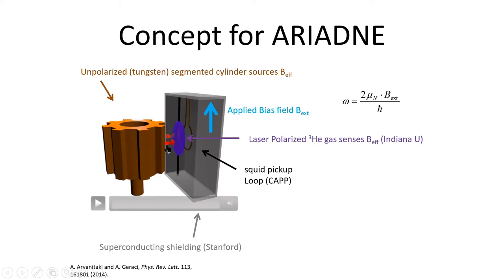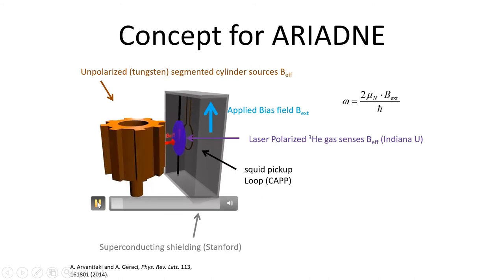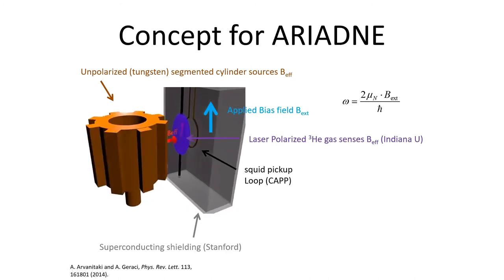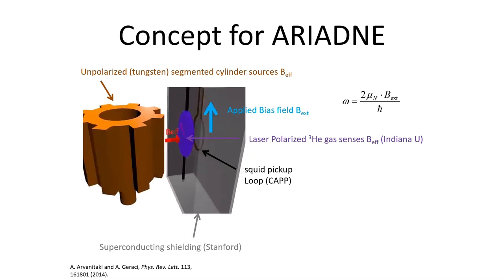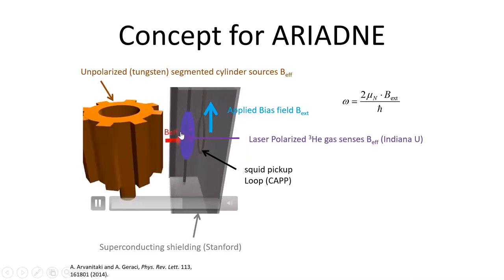And so the sample volume is enclosed in a container which is coated with superconducting shielding. And so that superconducting shielding will prevent regular magnetic fields from penetrating through, but not prevent this axion-induced magnetic field from penetrating through. So the idea is that we take this source mass and we arrange it so that it has a gear shape and has these teeth. And so as we spin the source mass cylinder, the teeth of the cylinder come by, and every time a tooth comes by, it basically modulates the strength of this effective magnetic field.